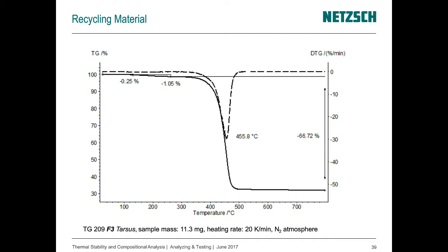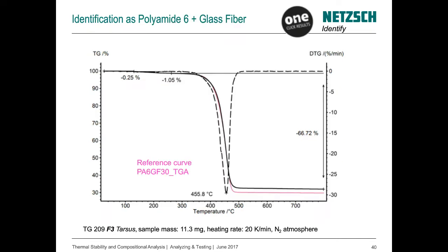And the first step is to find out what kind of polymer it is, and you know already that we can use the identify functionality for this purpose. If we do so, we see that we get a very good correlation to a reference curve of PA6 with 30% glass fiber content. The temperature position is very similar, only the filler content is a little bit different.